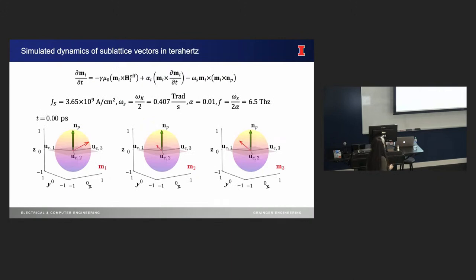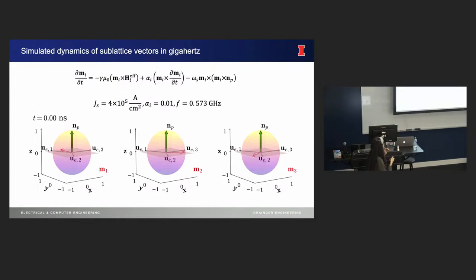So we simulated the terahertz dynamics. We apply a very large current and we get dynamics at 6.5 terahertz. This is how the three moments, M1, M2, and M3, are oscillating on the phase space, and it's rather fast. Then I do something unique. I reduce the current to about 10 to the 5. It's very small, four orders of magnitude smaller. Will the system oscillate? Yes. And that's what we demonstrated.